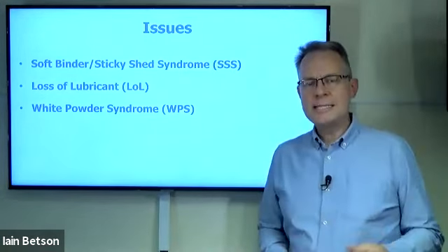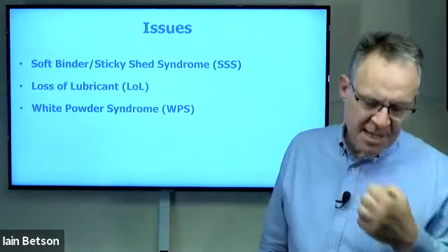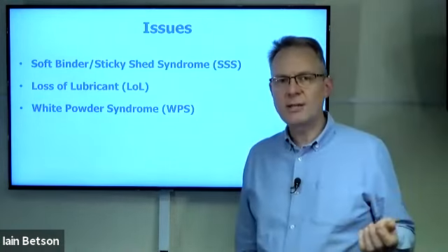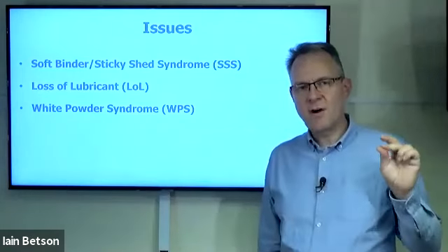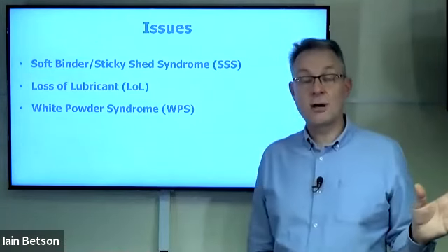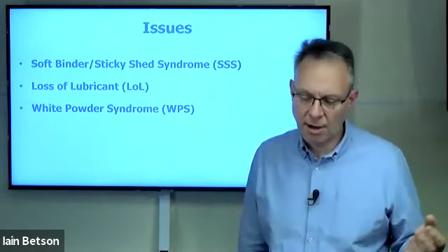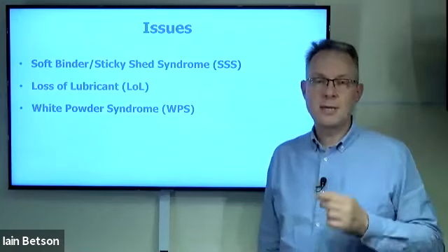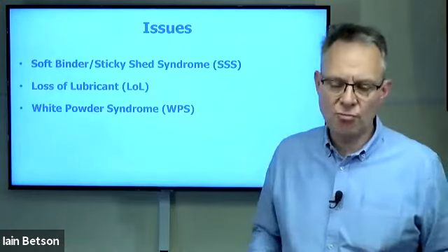So what is that? Well, what happens over time, a tape, no matter how well it's stored, will absorb moisture, just as a piece of paper, if you leave it, will start to absorb moisture. So the binder survived, the backing survived, but the binder absorbed the moisture, and as a result, when a tape went through a pass on a tape machine through all the tape guides, it literally scraped the oxide off the tape and of course ruined the recording.